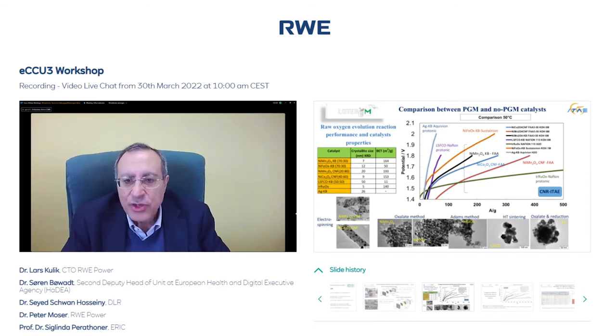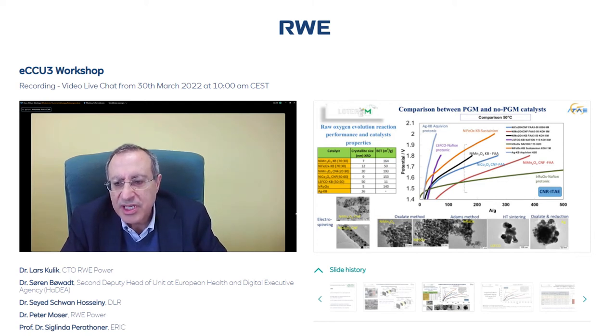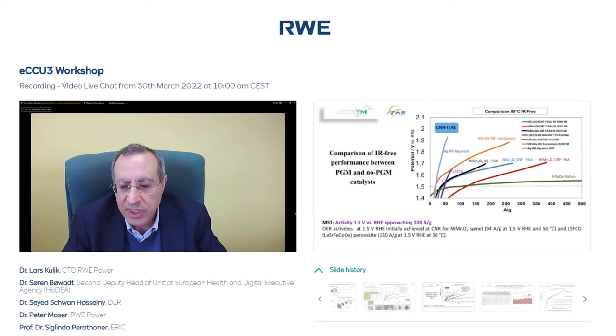Slide number four, please. So in the first phase of the LOTER.CO2M project, we have screened a large number of catalyst formulations, essentially precious metal electrocatalysts in the acidic environment and non-precious metal electrocatalysts in the alkaline environment. And of course, we have prepared these catalysts with different morphologies. Some catalysts require high temperature treatment, so you can see some sintering degree, but other catalysts can be prepared in a really dispersed form. Of course, we have achieved a variety of crystallite sizes, in general lower than 10 or 20 nanometers, and BET surface areas above 100 square meters per gram.